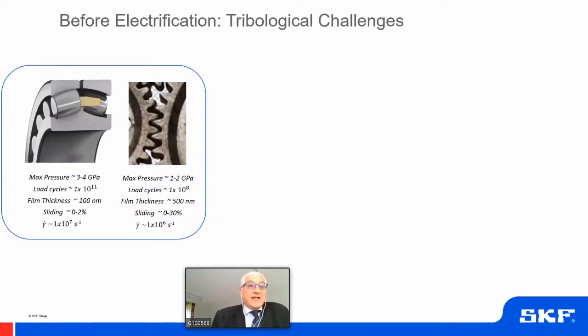Let us just have a look at bearings and gears. If we talk about bearings, you can immediately see that the normal operating conditions in bearings in automotive applications take loads which go from 3 to 4 gigapascals pressures. This is really high pressure. The number of load cycles that these surfaces have to endure can be up to 1 times 10 to the power 11. The film thicknesses are very low, about 100 nanometers.